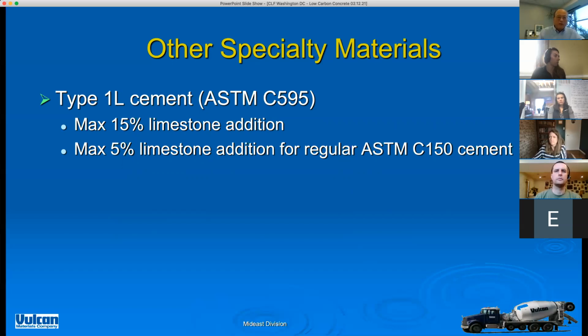Now that's compared with 5% maximum for regular cement that we use. But the cement companies typically don't go to the max. It all depends on cement chemistry and so forth. At the end of the day, the cement companies want to produce a cement product that has optimum properties that the customer likes. So I know locally there are two sources of type 1L cement. I think they're adding about 10 to 12% limestone. They don't go quite up to 15%. Likewise with the regular cement, they don't go to 5% either. They're somewhere in the 2 to 3% range. So like I say, it's available in the market,